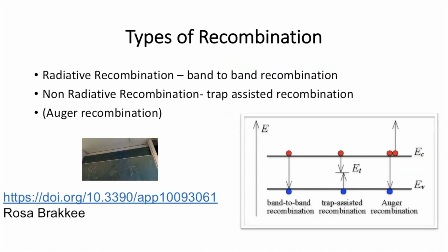There's one thing that I recently learned over the last few years, and that is radiative recombination. So that is not losing charges through trap states. The HOMO and the LUMO, you have the valence band, the conduction band. Light creates charges. These charges, you want them to move around. But if they can go nowhere, if they cannot go to an electrode, then they keep wandering around. And you want them to wander around until they find each other again and emit light. That is what we call radiative charge recombination.